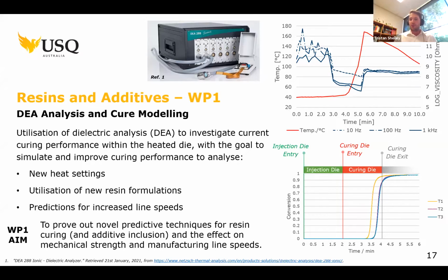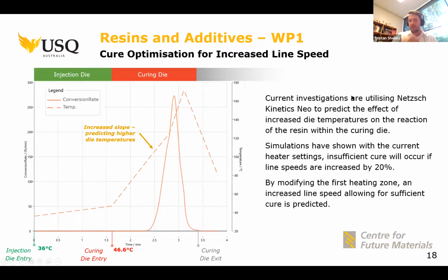So what we're looking to do is to fully understand the curing of the pultruded products through the dies currently, but then to formulate some new methodologies to improve and accelerate that cure through the pultrusion die. One of those techniques is to increase the temperatures within the curing dies. Currently, a ramp is used with a set temperature at the start and a set temperature at the end. But by increasing the slope of the temperature ramp, which shows an increase in the first heater zone setting, we're able to show that we can kick off the resin, we can start the resin curing earlier within the curing die, which then allows us to be able to increase the line speed of the pultrusion process.